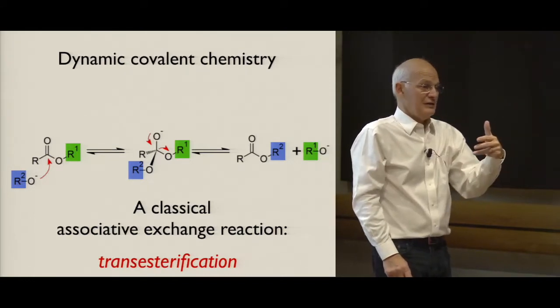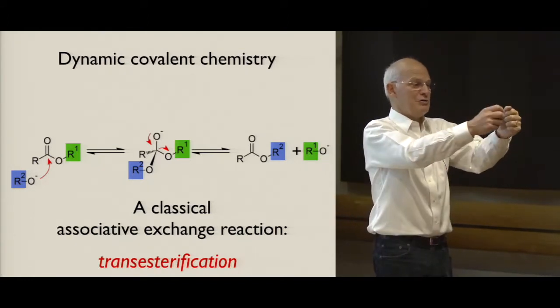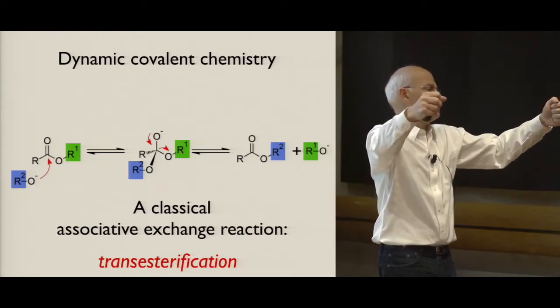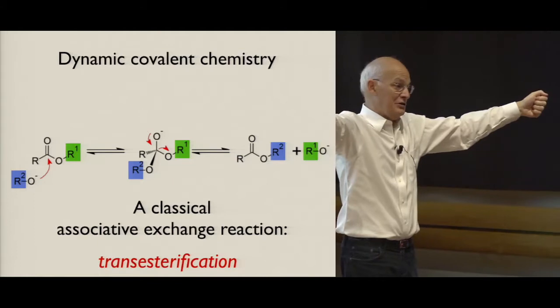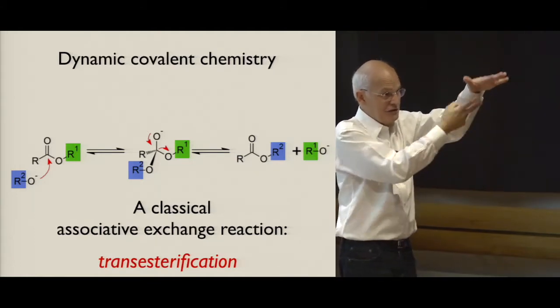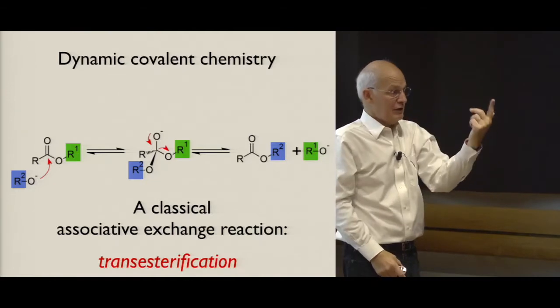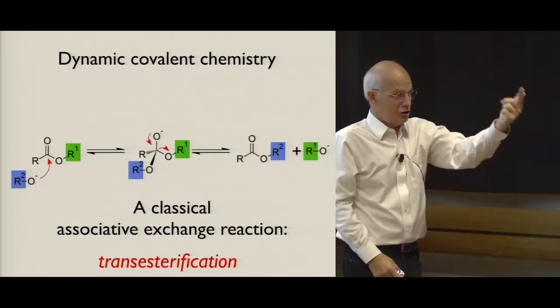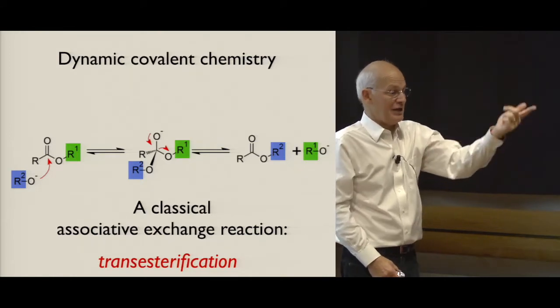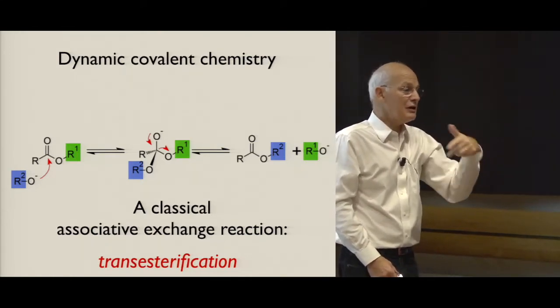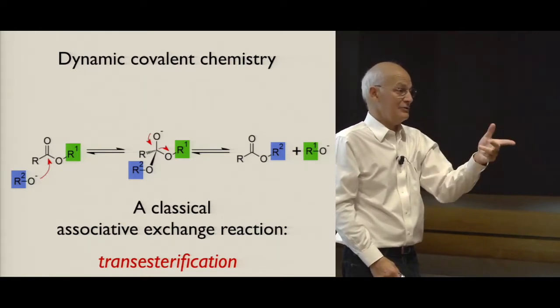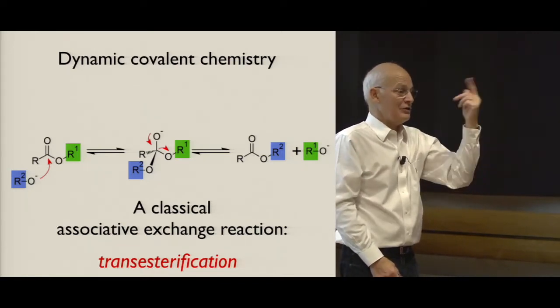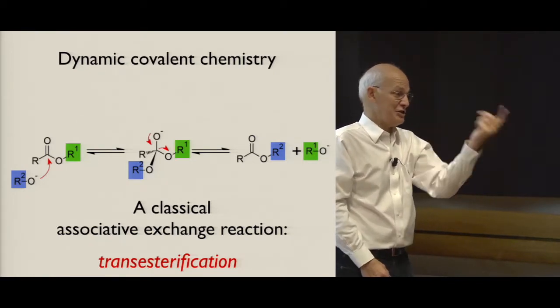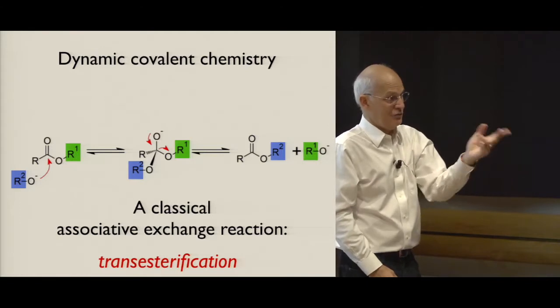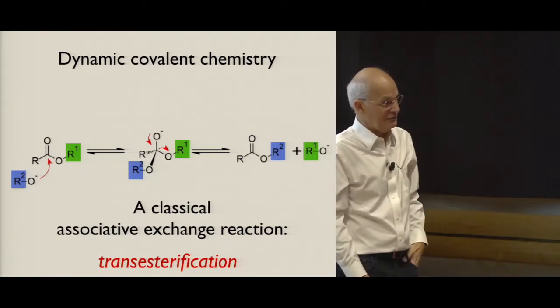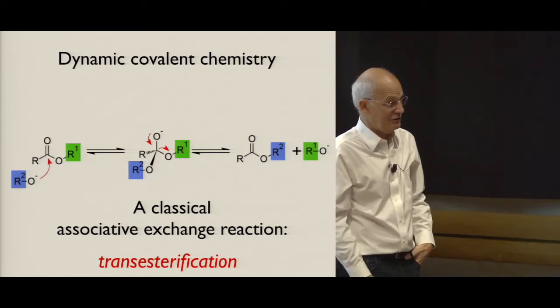The problem is that if you want to make a rubber, what you don't want is that when you heat, the system will be deformed permanently. So it's always a problem between the service temperature and the temperature you look at. So you would like to have a chemistry in which you can block the catalyst and block the reactions again, and then you can think about different triggers. You can think about light, but then the material has to be transparent. You can think about pH, and by changing pH, your catalyst becomes non-active or active. So all this is still open, but you are right.